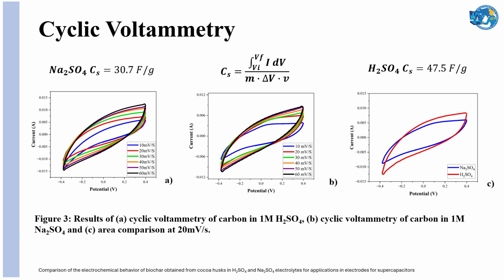Using the equation to calculate the specific capacitance, it is possible to calculate the specific capacitance for this material, and it was calculated in sodium sulfate and sulfuric acid as 30.7 farad per gram and 47.5 farad per gram, respectively.